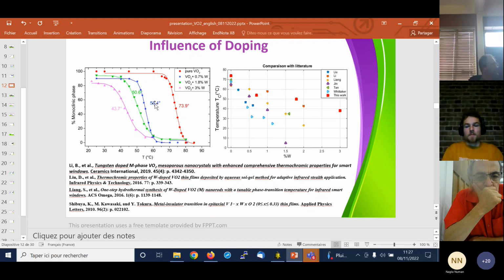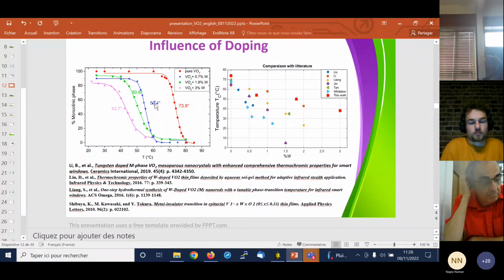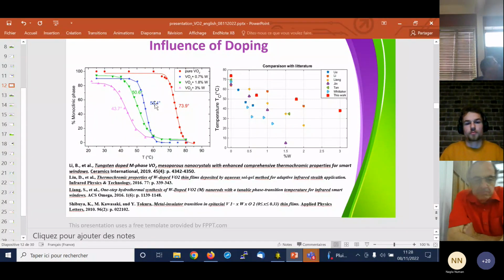So it means that if you look carefully at this diagram, at let's say 25 degrees, you have only 80% of the monoclinic phase. So 20% is still remaining in a metallic phase. That's what we understand from this diagram about what is going on. And the more you dope, the less pure the monoclinic phase you get. So this explains in some sense what's going on, and you can see also that it becomes less sharp. The transition is more rounded when you increase the doping content than if it's pure.